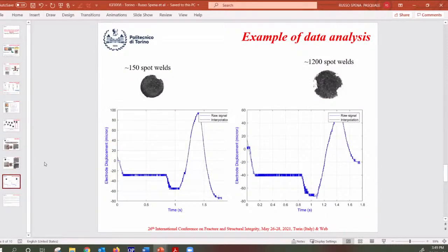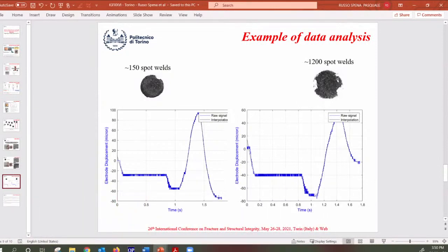The aim particularly was to correlate some welding signals to these features, in particular to the mechanical strength and the fracture mode. At the moment, we have only examined the signal coming from the electrode indentation. You can see how the electrode wear, and so the corresponding strength of the welds and the type of fracture, can be related directly with electrode displacement, showing that for some joints we have a large electrode displacement with respect to a worn electrode. This is due to the fact that worn electrodes can promote higher interface electrical resistance with different electrode displacement. In particular, the aim was also to examine the other signals in order to correlate, during the welding process, the manufacturing process and the type of joints obtained.